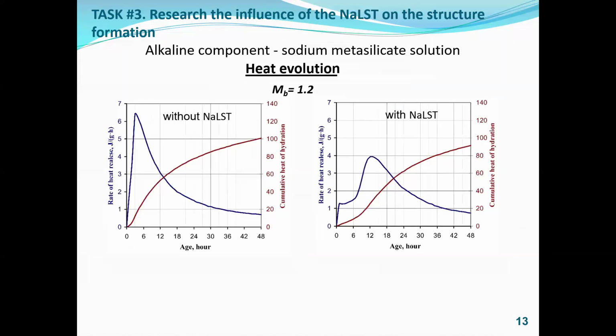Task 3. Research the influence of sodium lignosulfonate on the structure formation. The influence of the sodium lignosulfonate admixture was studied using alkali-activated cement with modulus basicity 1.2 made with sodium metasilicate solution, with account of its weak setting. The quantity of sodium lignosulfonate was 4% by mass of the cement. Increase in duration of the induction period as well as decrease in rate of hydration and degree of hydration reflect the retardation of structure formation processes.